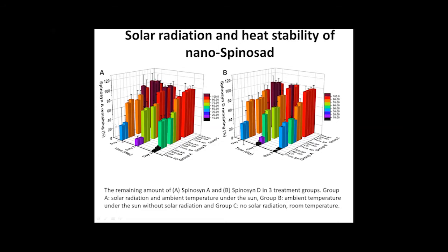In groups A and B, all 4 samples exhibit gradually decreased spinosad A and spinosad D amounts with time increasing, while no significant spinosad degradation occurred in group C, suggesting both solar radiation and high temperature would decompose spinosyns. In group A, bearing both solar radiation and rooftop high temperature, both of the 2 nanospinosad formulations demonstrated greatly improved spinosad protection than the commercial spinosad product and pure spinosad. This indicates both rough and smooth nanocarriers can give the protection.